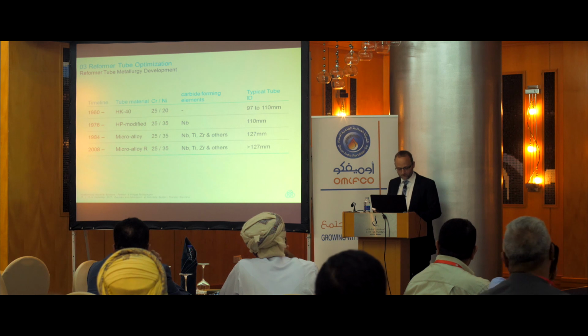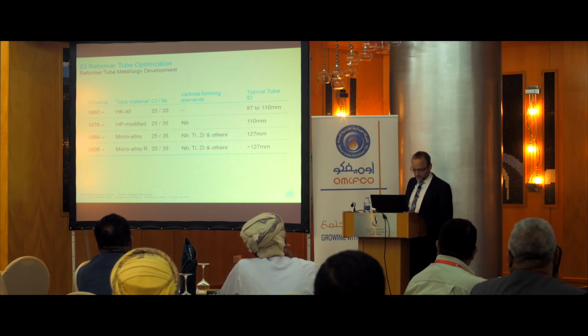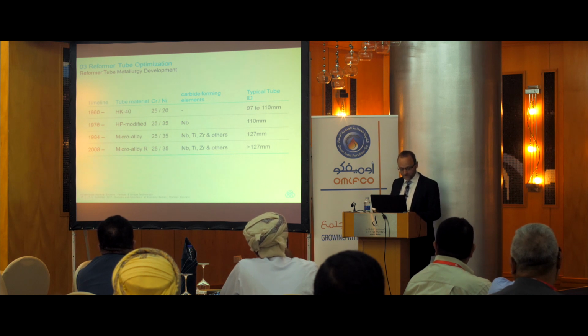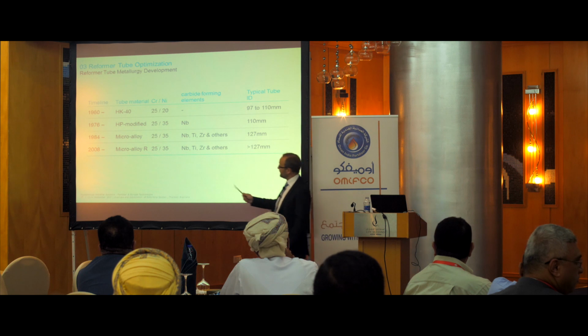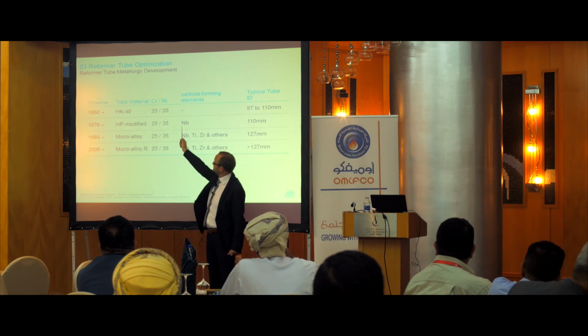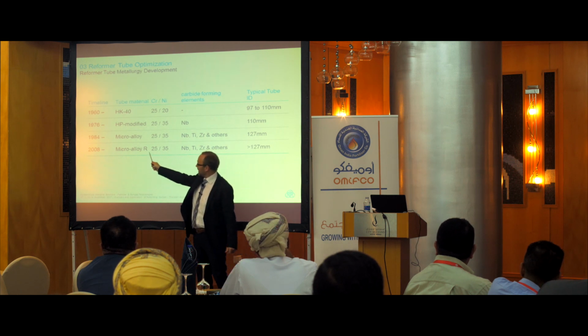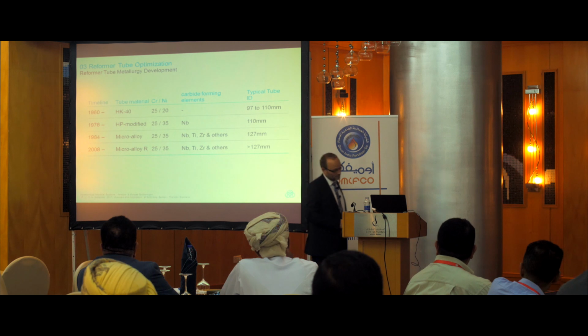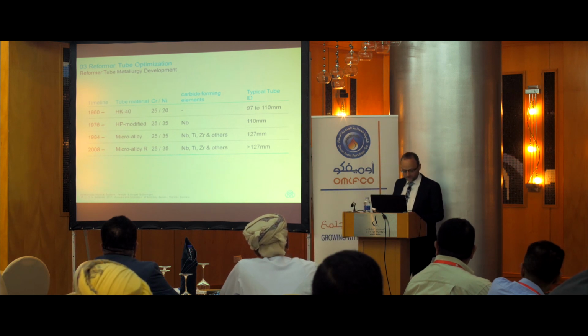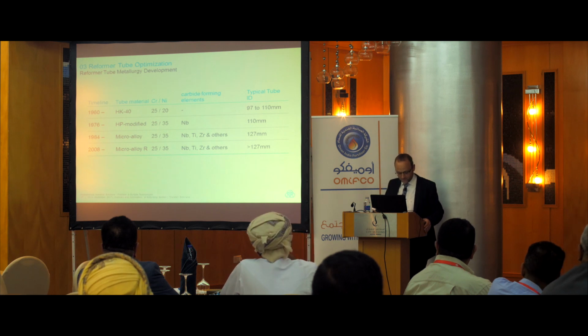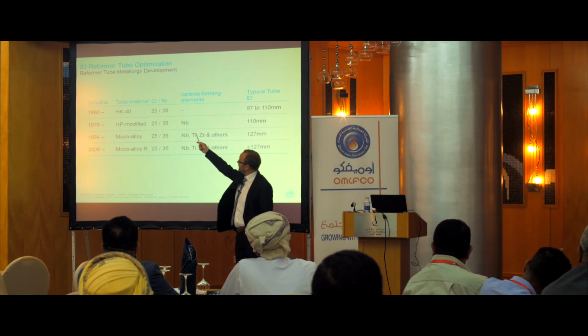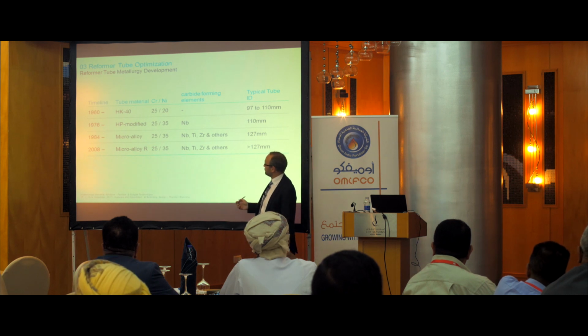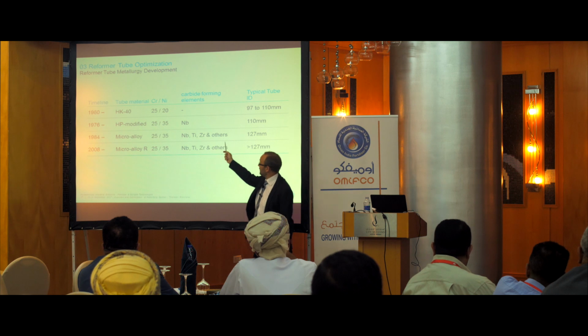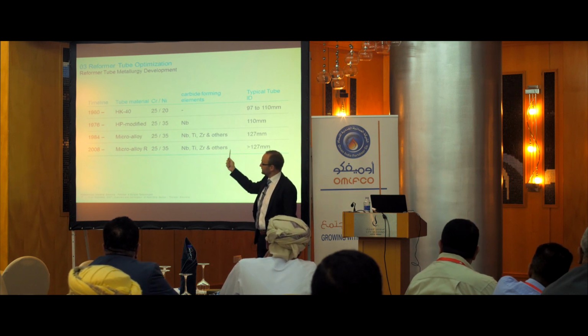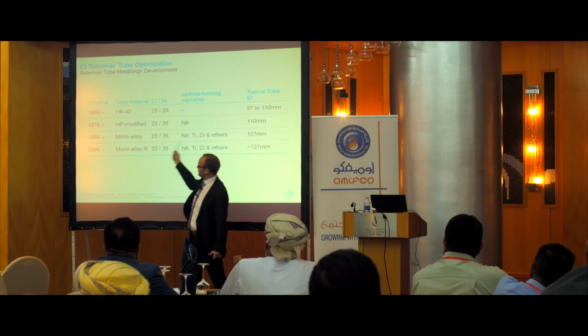This table shows the main steps in reformer tube material development. The latest evolution stage of the centrifugally cast HP grade, which is 25% chrome, 35% nickel, is the so-called microalloy grade. Since creep strength at these elevated temperatures depends on the carbide distribution and stability, tube manufacturers have, over the years, added first niobium and then other small quantities like titanium, zirconium, and of course some rare earth materials to their tube metallurgy. And because of these small quantities, these alloys are called microalloy.